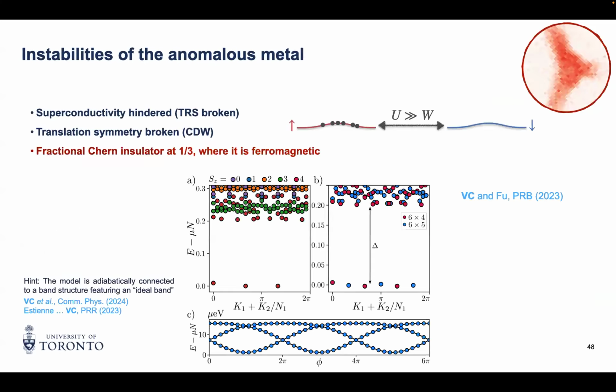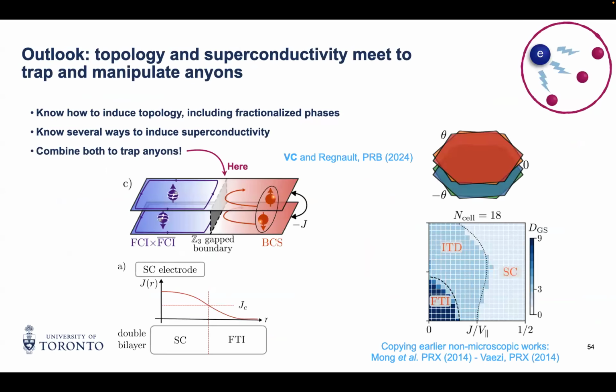Then if you really want to go to the quantum computer side, there's, I think, one way to do it, which is you want to trap those anyons and then do operations on them. Operation on anyons is braiding them. So first you need to trap them, localize them, and then you need to move them around. I think you can localize them as follows. Create two copies of the state that we've just seen, a ferromagnetic quantum Hall state and a ferromagnetic quantum Hall state in the opposite direction. Proximitize it with a superconductor. Then at the boundary between the two, the system will be gapped and will host trapped anyons on the corner of that line boundary. So that's the way you trap them.